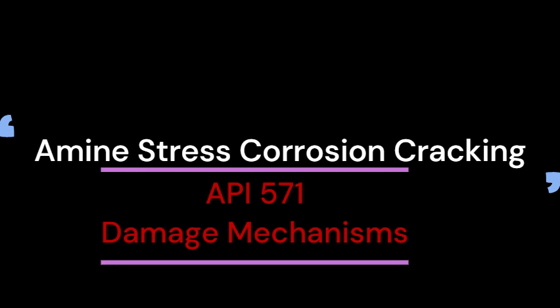So short bursts of the wrong conditions on stressed steel can be enough to start cracks. Precisely. Those short exposures can hit that non-PWHT steel with wet amine at maybe an elevated temperature from the steam, and boom, you initiate cracks that might grow later. That risk is why the industry basically says, just PWHT everything in amine service if you can.